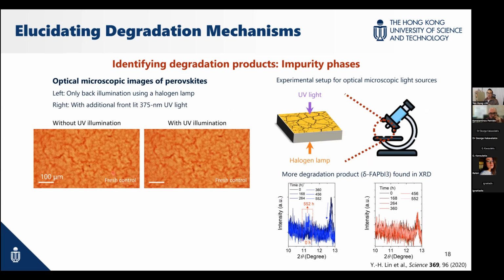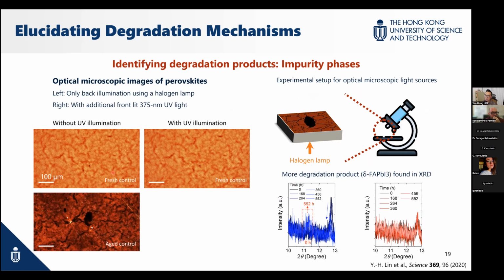So this is a fresh control sample. So we see no difference. This is an aged control sample, exactly the same conditions under the same microscope, but it's darker. Why? Because when the film is aged, it becomes rougher, and so the light will scatter, so it's darker. But of course, there are many more features that we can see here, like colloids.